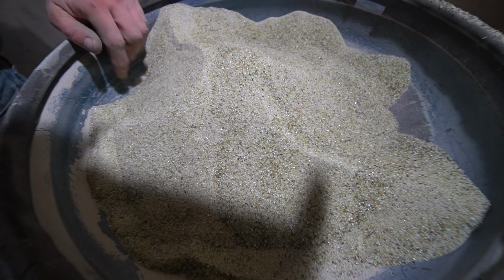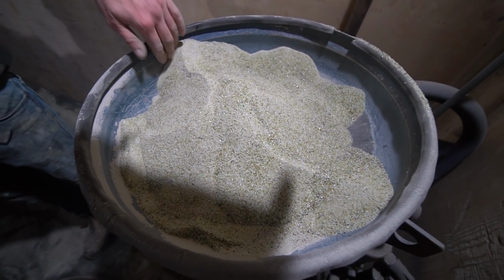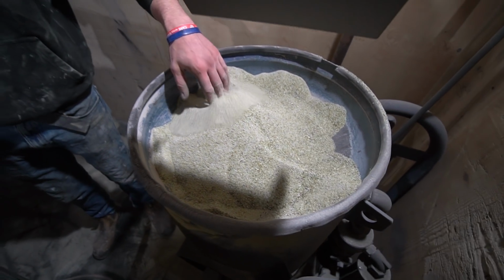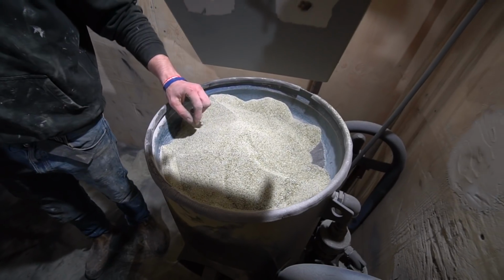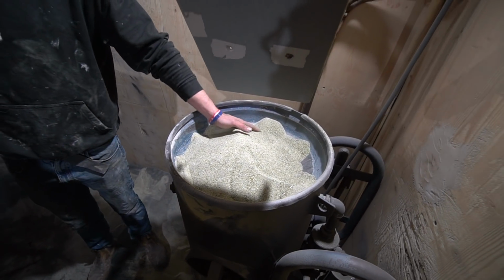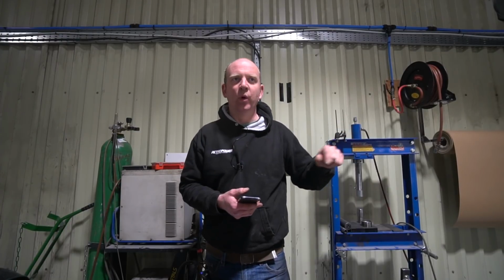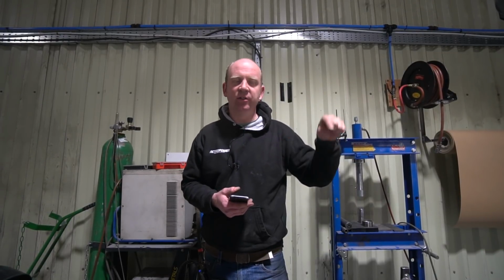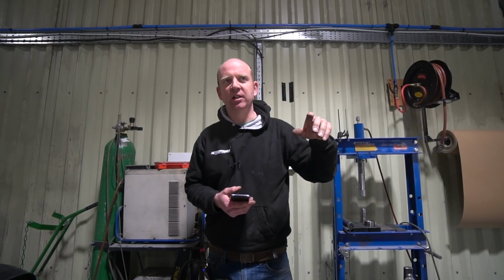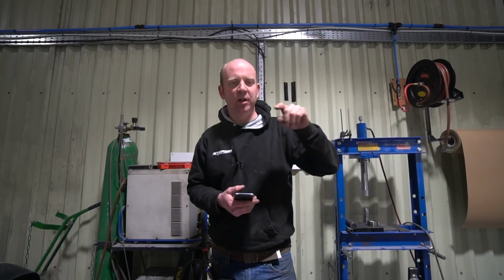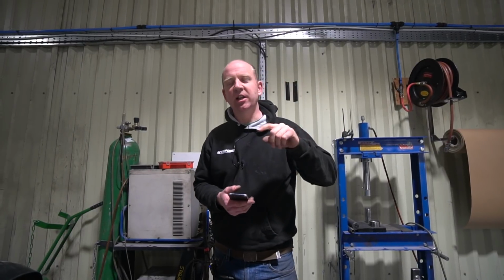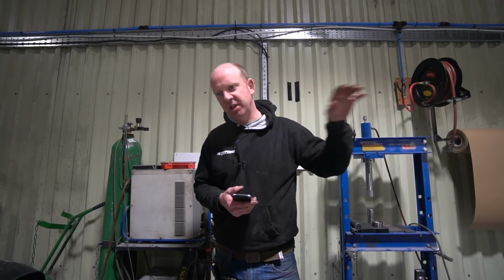So what we used to do was buy a mixed grit in. We don't now. We buy what's called a medium. I can't remember the exact particle size. It's what the supplier terms as medium grit. We buy that in, which is actually at the coarser end of what we would want, but we remix it with screened previous grit. And I actually built a vibrating screen deck, which we'll just show a shot of in a minute. Built a vibrating screen deck, and when we finish blasting the car, we shovel all the grit up